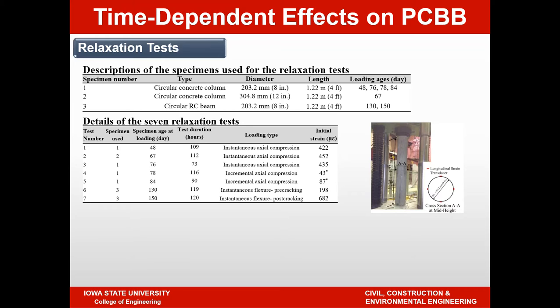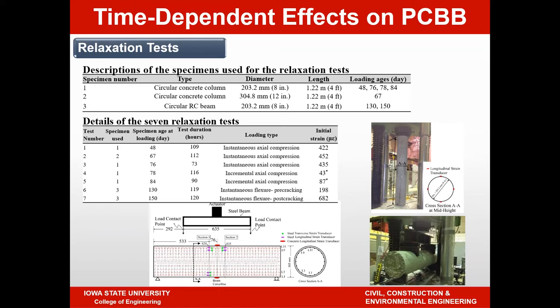A number of tests were performed using these three different specimens. The age of loading was varied, the duration of loading was varied. In five of the seven cases, we applied axial compression. In two cases, they were subjected to flexural moment, in one case before the beam cracked, in the other case after the beam cracked. So what you see here is an axially loaded column, and both of them did not have any reinforcement inside. It's just pure concrete, and we wanted to get a feel for how they perform. In the beam, though, we had longitudinal reinforcement and spiral reinforcement, and the reinforcement also had some strain gauges to capture the change in strain